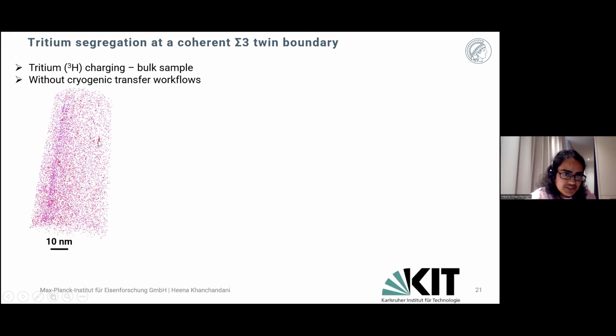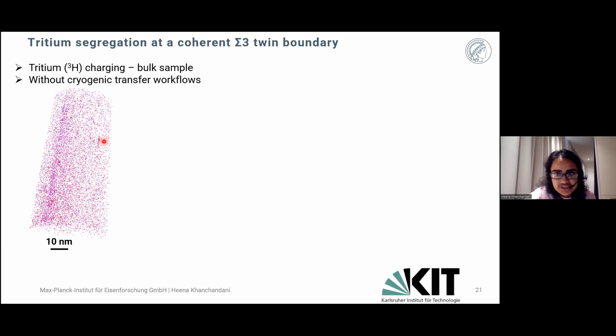Yeah, this one you mean at these particular dots. This could also be from the sample analysis conditions or sample preparation maybe. But also it can come from the charging, that the charging was not homogeneous. Like there are some defects or interstitial sites, as you say, at these sites where the tritium is segregated, but we could not really find out what these sites are. I mean, they don't look like dislocations, and this is a recrystallized material in which we do not expect any dislocations. So the grain boundary can be interpreted, but these could also come from the analysis or sample preparation conditions.